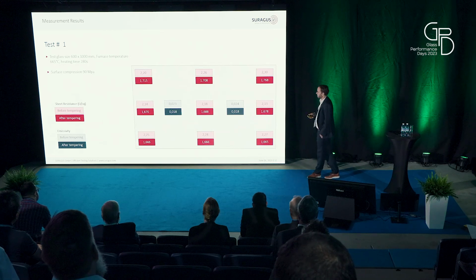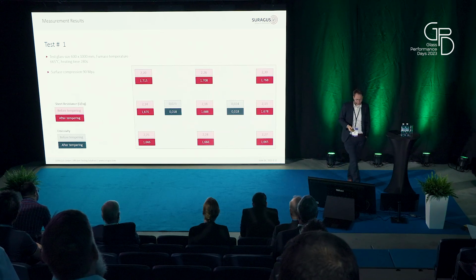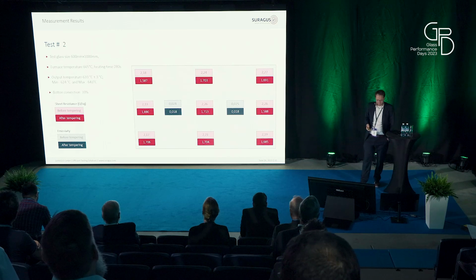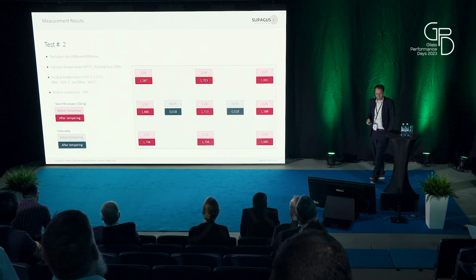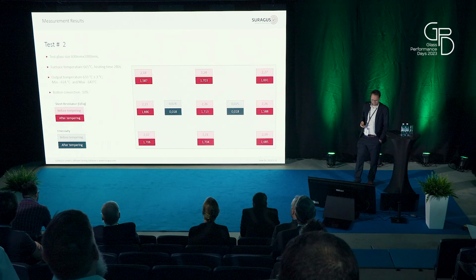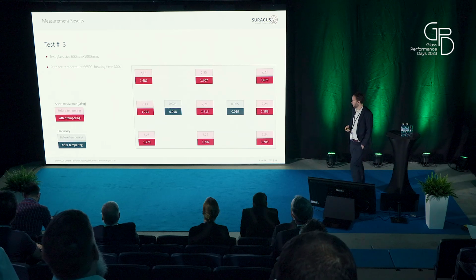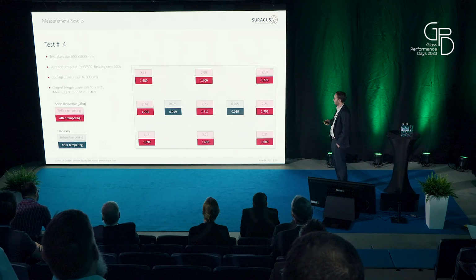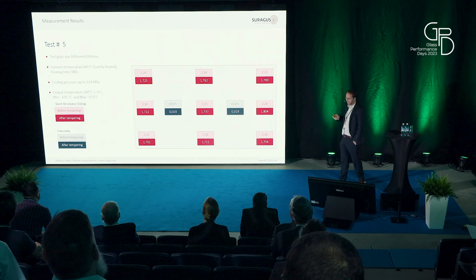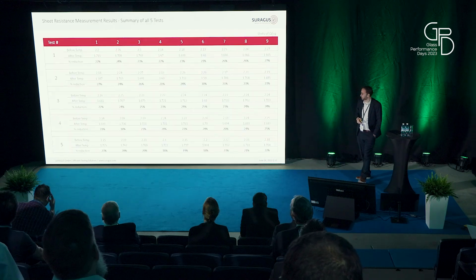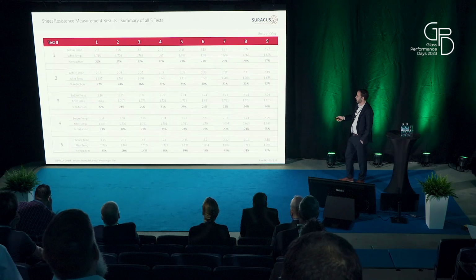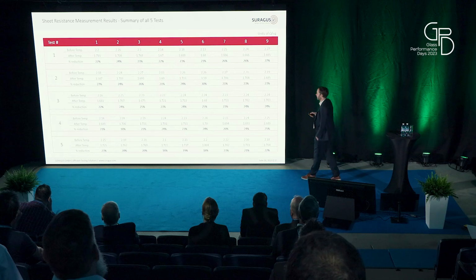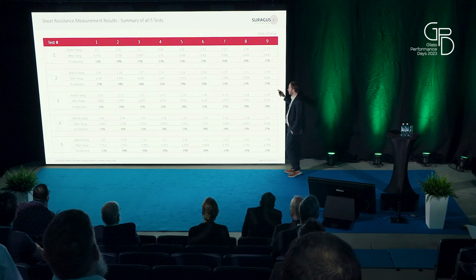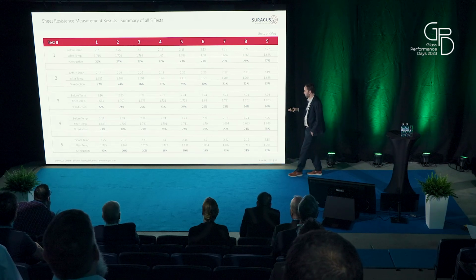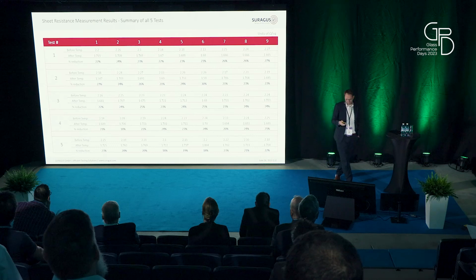This is now the first test, and we've done this with the same glasses and different glasses, different heating profiles, and also different glass thicknesses. So there are different results here, which I've just run through. The overview is here. In this type of glass, I don't say the glass type here, but basically we have an improvement which is roughly 20 to 25%.